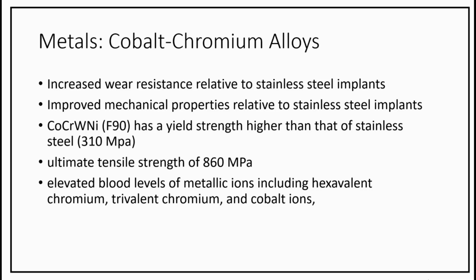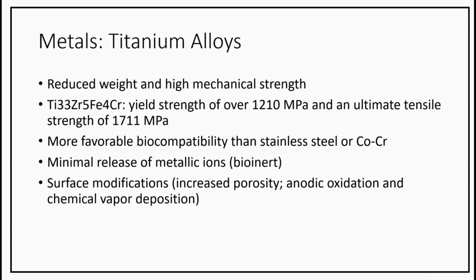A common cobalt-chromium alloy product, CoCrWNi (F90), has a yield strength higher than that of stainless steel at 310 MPa and an ultimate tensile strength of 860 MPa. It has been noted that long-term wearers of cobalt-chromium implants show elevated blood levels of metallic ions including hexavalent chromium, trivalent chromium, and cobalt ions, a mix of potential and known carcinogens.